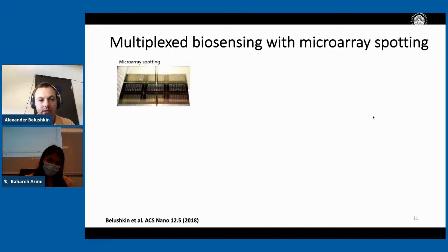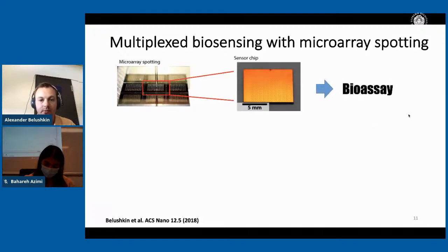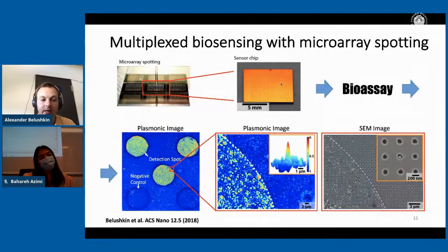For this, we use a non-contact piezoelectric spotter, where on every chip we make an array of hundreds of single spots, so that when we perform the bioassay, we can detect different things at the same time. As you can see here in the bottom left of the image, we have 3 spots with the antigen of interest and 2 negative controls, which are just non-specific mouse isotype IgGs. And we can zoom in on the plasmonic image, so we can see here those individual spikes, right?